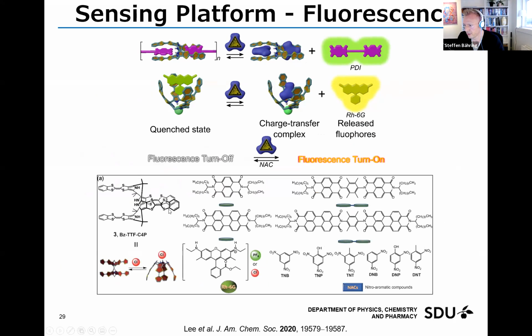So you can see here that we have the benzo TTF, and then we applied the naphthalene diimide and the perylene diimide fluorophores. And we can make them as monomers and as dimers. And this investigation showed that all of these systems could be applied as indicator displacement assays, but with varying efficiencies. So some of them actually gave a fluorescence turn on, and some of them gave a fluorescence turn off.